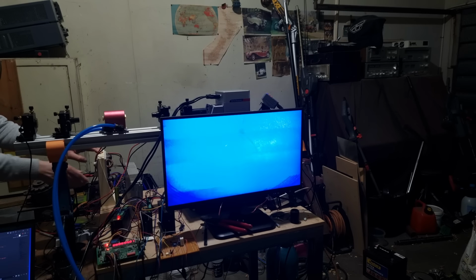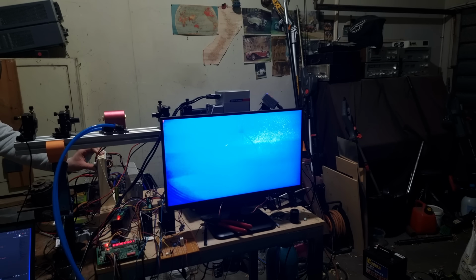Now, since I was using a diode pump, I had around 200 watts of power on tap, but what I lacked was the fidelity of a fibre or YAG laser, meaning that I couldn't focus the laser as tightly as many professional systems can, at least not without a large degree of stray light. So I'd figured that if I could bring the spot size down to 50 to 80 micrometers, with a similar power density, I could get away without a pressurized atmosphere. And it would turn out that I was right, but for the wrong reasons, but I'm going to explain why a little further down the track.